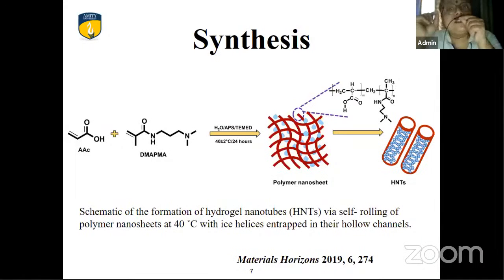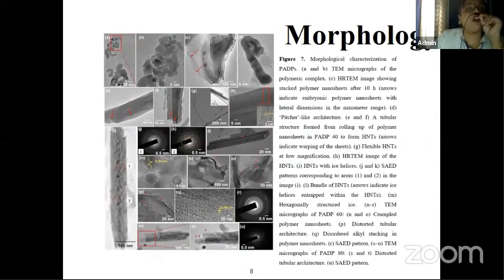But nobody looked inside. So we, for the first time, started the work. It is not that we started in 2019; we started the work in 2015. We have done XPS, XRD, TEM, AFM, and then we tried to understand the mechanism for the formation of these exotic nanostructures, that is hydrogel nanotubes with ice helix. That we have shown with this morphology.